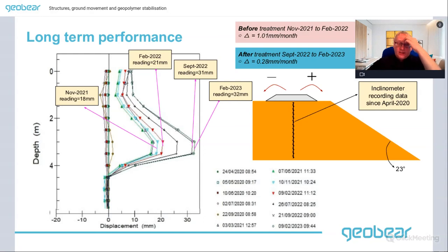We also did some testing using an inclinometer, and the inclinometer readings showed that the rate of deterioration had greatly reduced before and after the treatments, with the measurements indicating the rate of movement had been reduced by 72%. Because it was only a test section, we didn't do all 80 meters of the embankment. There was still some residual movement, but significantly less than the previous condition. It did actually enable the railway line to be reopened at a slightly higher speed, and the customer was very happy.